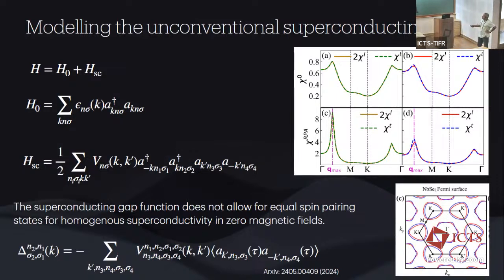Again, you start off with a Hamiltonian, which is the tight binding Hamiltonian corresponding to the 3 orbitals. And your superconducting pairing kernel is this quartic term out here, which has been kept completely generic. No particular symmetry channel has been assumed for it. And this, then, if you do a mean field decomposition of it, leads to a gap function, which would be of this form, which all of us know. This is just a generalization of the BCS theory that you do.